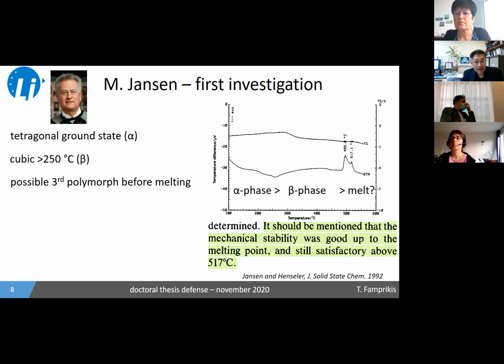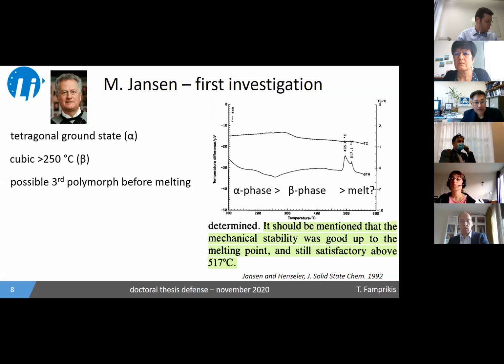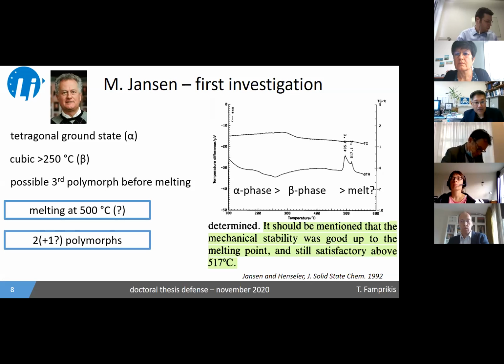Very interestingly, however, they mentioned in this paper, and I'm quoting directly, "it should be mentioned that the mechanical stability was good up to the melting point and still satisfactory above 517°C." So this raises some questions as to whether the melting is actually at 500, which I'll come back to. So we have 2 + 1 polymorphs, and they measured a conductivity of the order of 10 to the -6 Siemens per centimeter, which is somewhat low in view of practical applications. The material somehow stayed in the dark for a little bit.